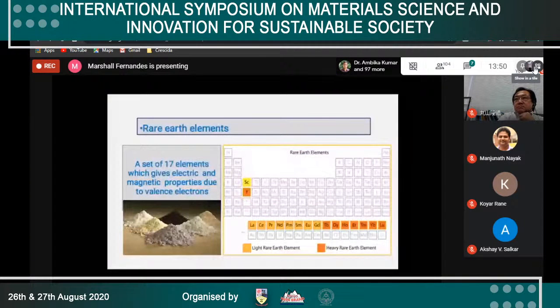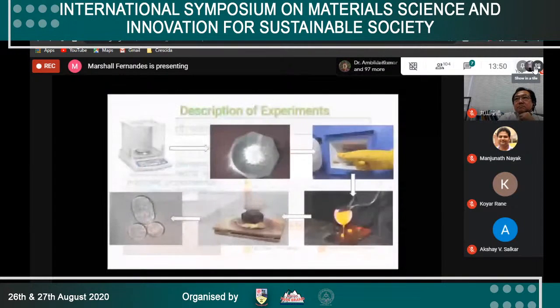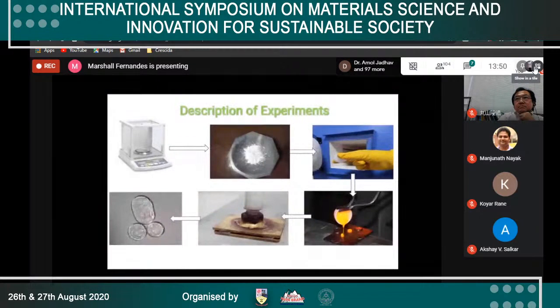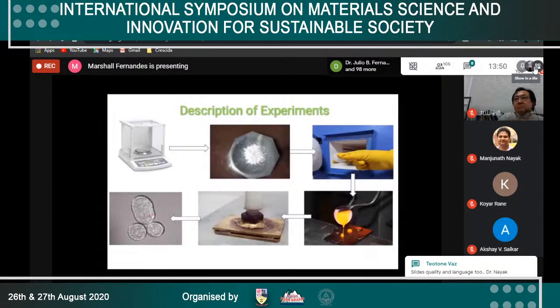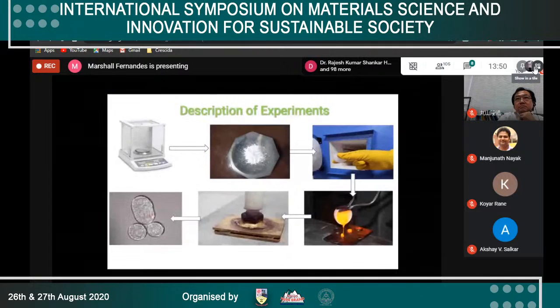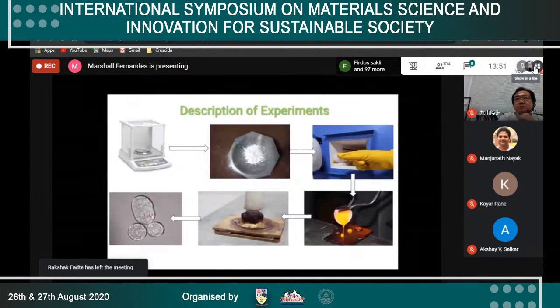In our experiment, first of all, we weigh the different compounds according to the composition. Then we crush all the compounds until a homogeneous mixture is achieved, put this mixture in a crucible and melt it in a furnace. Then we put the desired melt on a brass plate and quench it, and then anneal for some time, and we get the desired glasses. Now for the characterization of the glasses, I would like to invite Miss Anu.